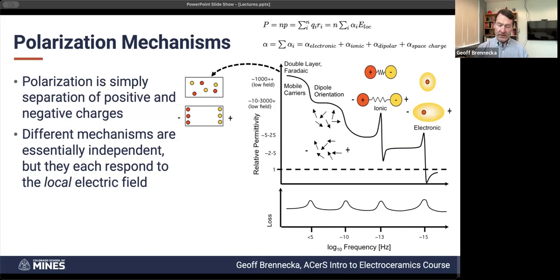You'll notice with the relatively sketchy numbers that are thrown on the vertical axis here, the relative permittivity, as I mentioned, associated with electronic contribution, with index of refraction, you might get a relative permittivity of 2 or 4 or even 5, something like that, just from the electrons. That's pretty small. From the ions, there are a handful of materials where you can actually get ionic relative permittivities as much as 30 or 40. But that's still relatively small compared to the values that you can get for these other polarization mechanisms.